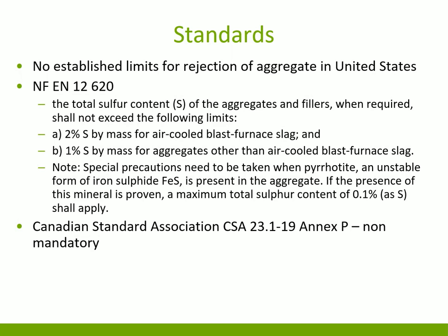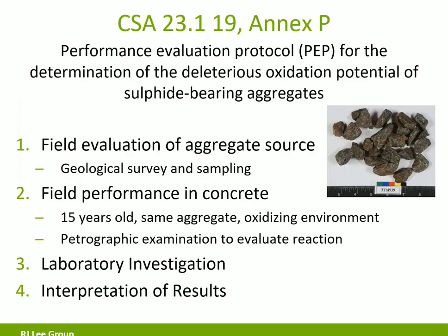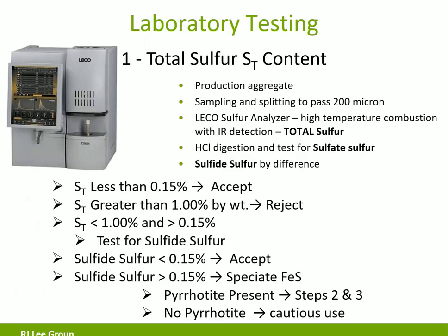So the laboratory investigation, you're first going to look at the total amount of sulfur in your aggregate. And from there, you can identify how much of that total sulfur is sulfide sulfur. So right now, based on some European standards and information we have, if your aggregate has more than 1% by weight of sulfur, it's going to be rejected, because even if it's just pyrite, it could cause staining problems and such. If your total sulfur is less than 0.15, you can accept it. If it's in between, you'll want to test it further. And first, you're going to test for the sulfide sulfur. And then you're going to move on and test the potential oxidation issue.